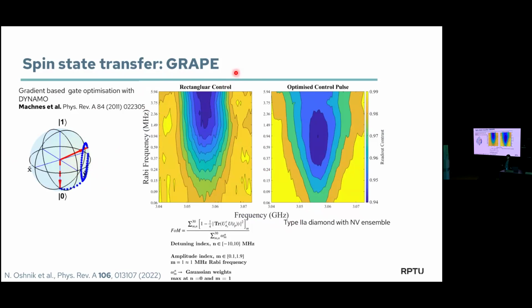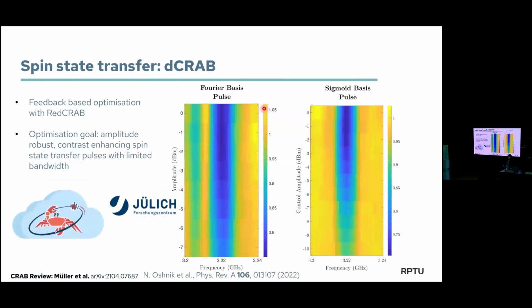So this is just a rectangular pulse. And then you go for the optimized pulse, and you see that with this optimized pulse, it's like you're going additional loops on the Bloch sphere to compensate for such variations. And you see that you get much better plateaus. You get better readout contrast. And you also get a more robust pulse.